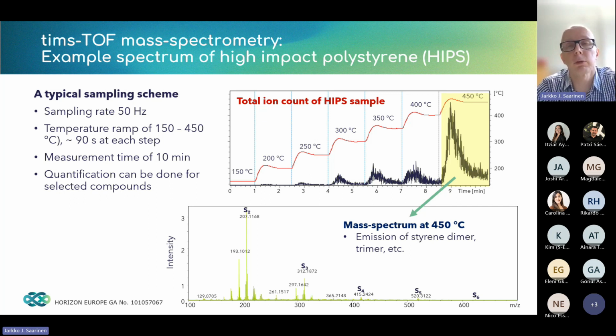So for the plastic samples, we have developed a protocol. We use a temperature ramp up from 150 C up to 450 C in 50 centigrade steps. The measurement time is roughly 10 minutes, so we stay 90 seconds at each of the steps. And the sampling rate of our timsTOF device is 50 Hertz. So every second we collect 50 different mass spectra out of the sample.